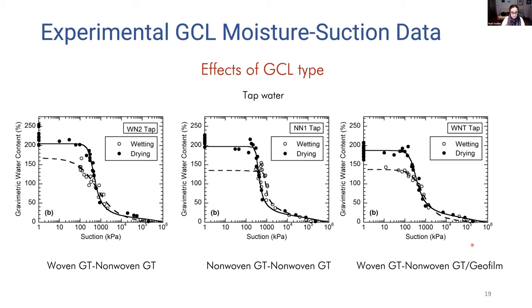geofilm as well. What we see here for tap water response, and this applies to the DI water and CaCl2 analysis also, is that the material behavior is similar. There are some minor differences in the response of the materials, but the changes are not as significant as the changes that we observed when we switched between different types of fluids that the GCL is exposed to.